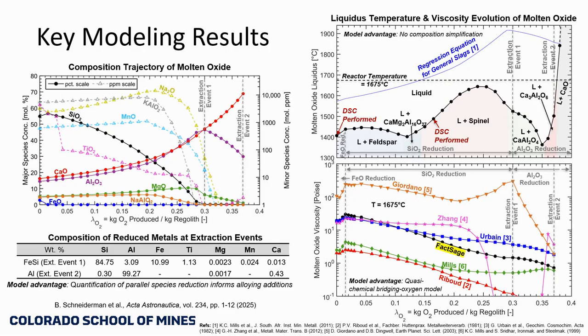On the table on the lower left, a couple important things here are at the point where we find it optimal from analysis to transfer or remove the iron silicon. You see the composition there. There is some aluminum in that. That is, aluminum begins to electrolyze while there's still iron and silicon present. And then in the final aluminum product, it is more than 99% pure aluminum, but with small amounts of silicon and calcium particularly. And that's actually okay. We'll find that the common alloys of aluminum do have iron and silicon and calcium in them, and you do want a bit of that to improve its workability, although you don't want too much.